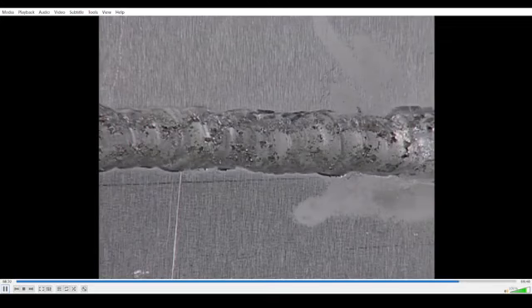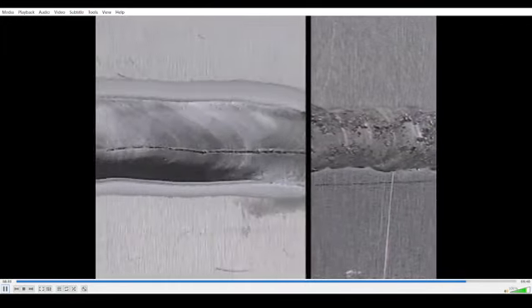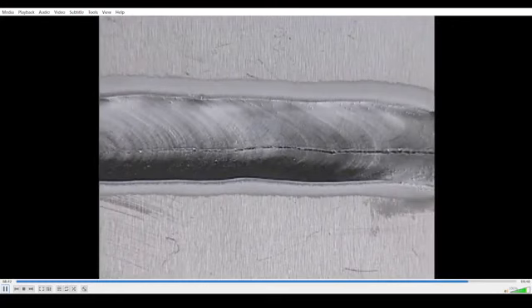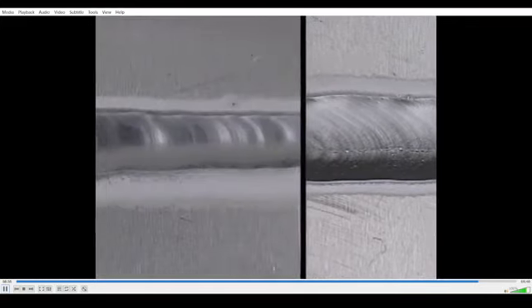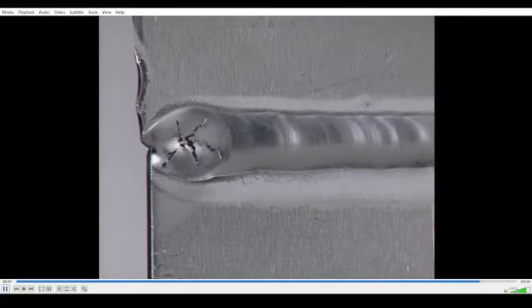This could be caused by too long an arc length, insufficient gas flow, damp gas, dirty base metal, or a contaminated electrode. Longitudinal cracks in the weld or along the toes can be caused by the mismatch of base and filler metals, insufficient shielding, excessively concave fillet welds, or too small a weld bead for the base metal thickness. Crater cracks are caused by not filling the craters sufficiently at the end of the weld.